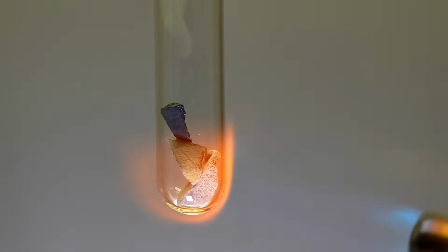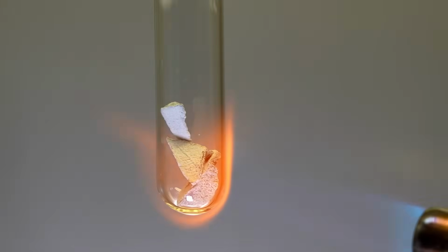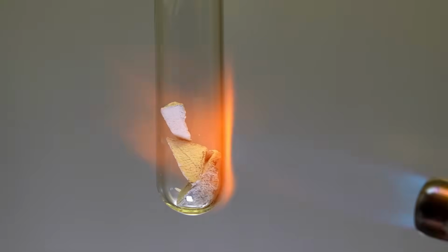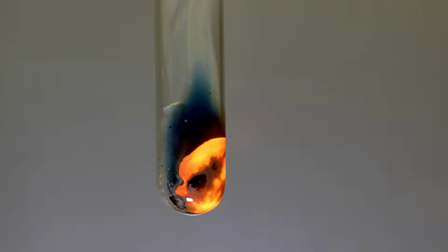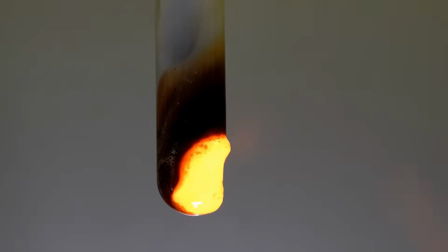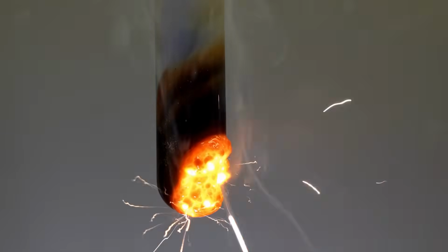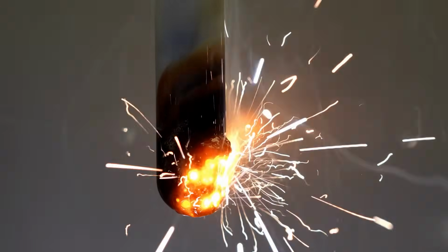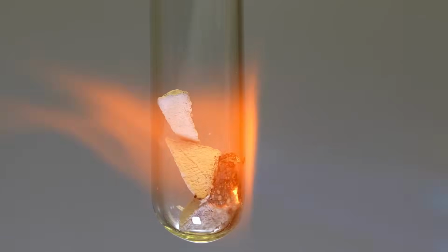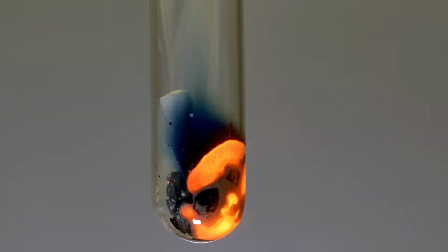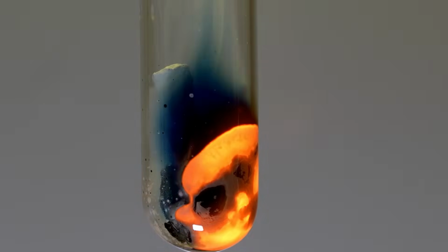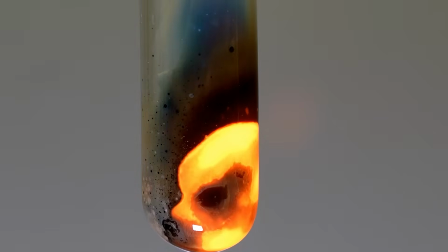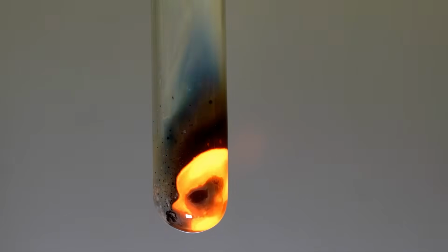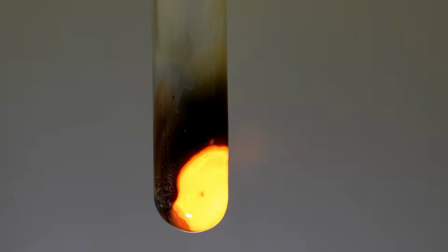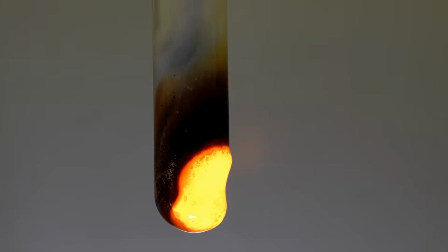First, I decided to heat metallic lithium. According to chemists, it shouldn't be heated in glass. I took the risk. After being heated, the lithium began to melt and started to react with the glass, which contained silicon dioxide. As a result of this reaction, pure silicon was produced. If you rewatch this moment, you can see at the start of the reaction, a small dark blue cloud formed. Perhaps these were vapors of metallic lithium, which managed to boil off at the start of the reaction with the glass. Even in an argon atmosphere, these vapors still managed to oxidize. It's possible that some oxygen seeped into the test tube.